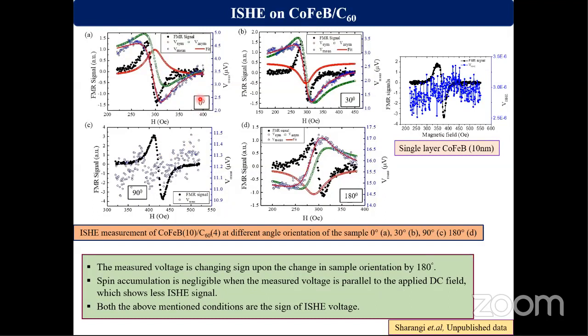So we have seen that at 180 degree, the ISHE signal gets reversed, which is obvious because at 180 degree the magnetic field direction is also reversed. And also at 90 degree, there is less ISHE signal. So at 90 degree, we are measuring the voltage parallel to the applied DC field. In this condition, the spin accumulation is less, so that's why there is less ISHE signal. So these above two conditions prove that there is spin pumping happening at the cobalt iron boron C60 interface.